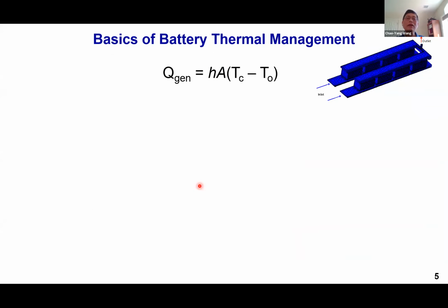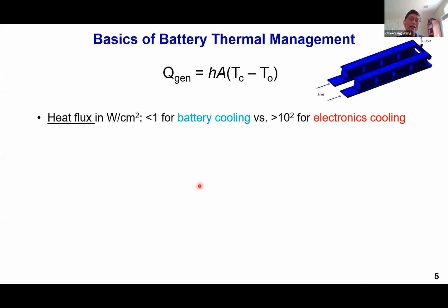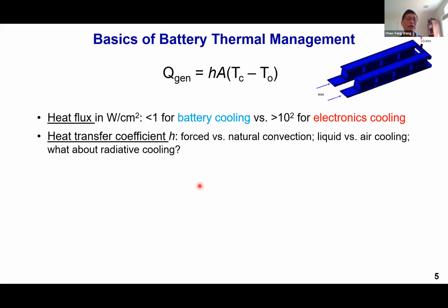So here again, let's explore a little bit more about this key equation and each of the terms involved. This gives you a lot of basic ideas about how to do thermal management. In terms of heat flux, expressed in the unit of watt per square centimeter, for battery cooling it usually is less than 1. A lot of times it's much less than 1. And that is compared to greater than 10 to the 2 for electronics cooling. So we're talking about 2 to 3 orders of magnitude easier job for battery thermal management, or for battery cooling.